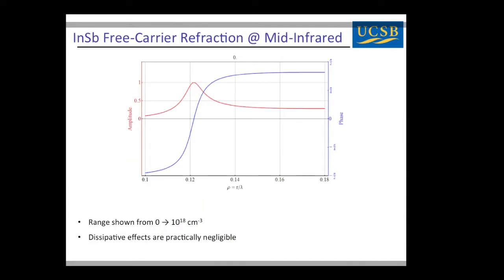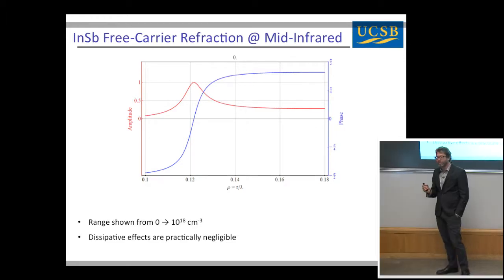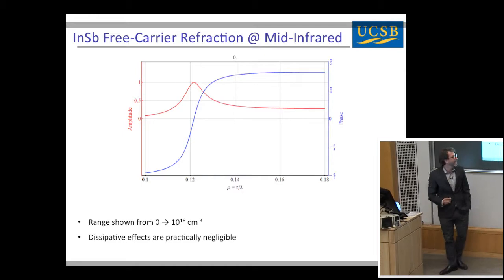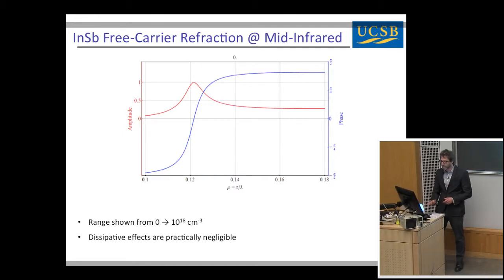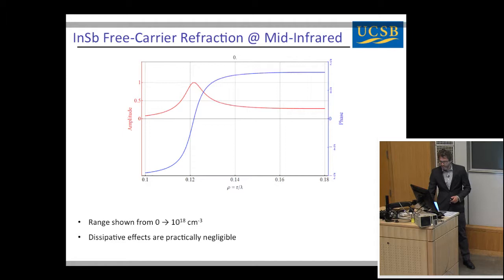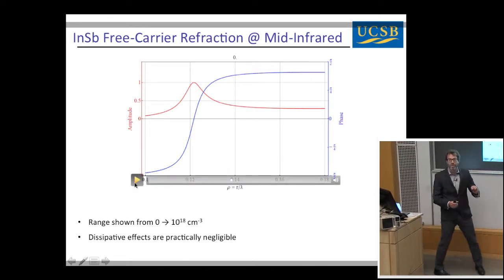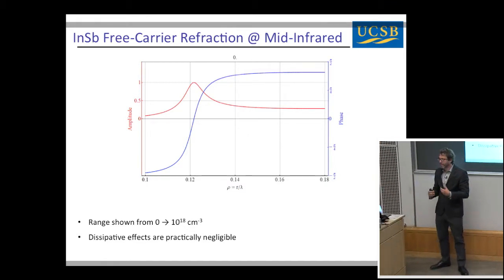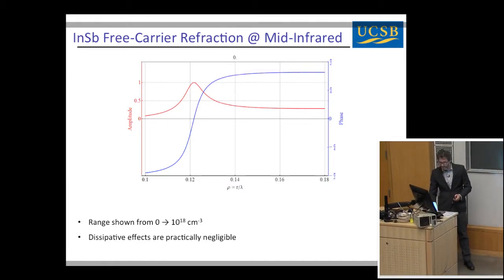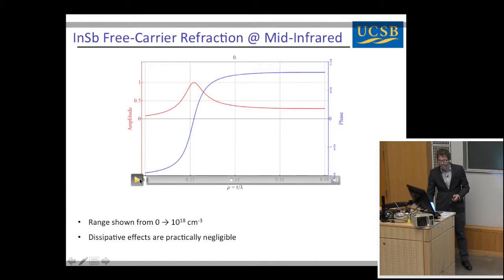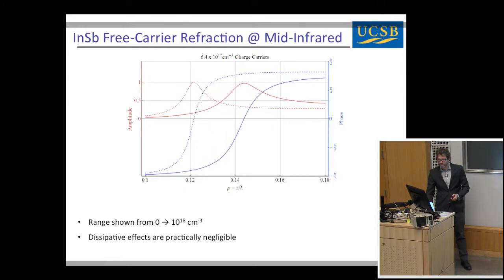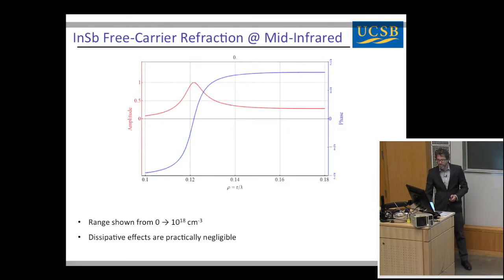Okay, so this is a plot of indium antimonide. We're interested in indium antimonide because it has a very low effective mass. Okay, so I'm showing you again, in red is the amplitude of the response, in blue is the phase. Okay, now I'm going to show you an animation where we look at how this curve evolves as we increase the free carrier density inside our semiconductor. Oops, let's go back.